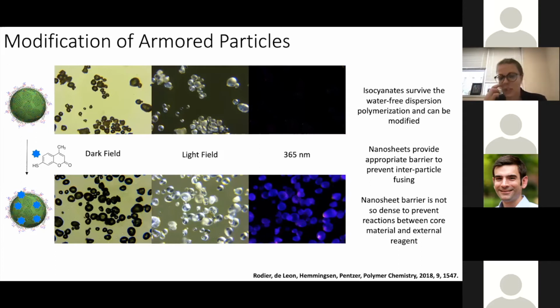But I think this tells us some really interesting things, and we don't quite understand the organization of the nanosheets at the interface. But the big picture is that the nanosheets provide a barrier to droplet-droplet coalescence, but they still allow mass transfer between the two phases. And so this is seen both here in the ability to functionalize, isocyanates that we expected to only be in the polymer core, but also in the ability to do interfacial polymerization and make that capsule structure.